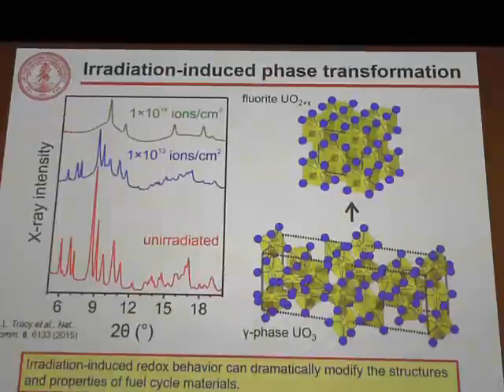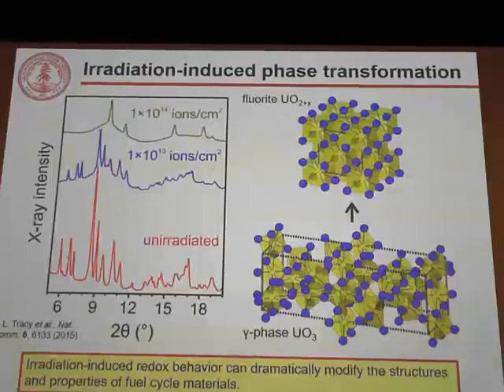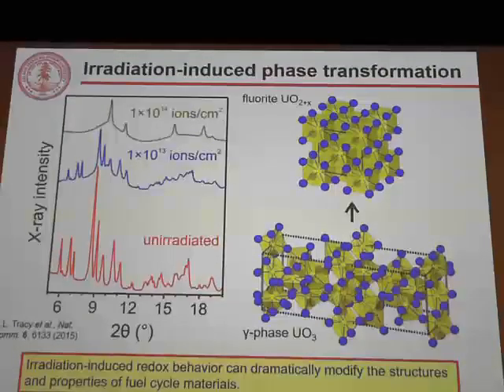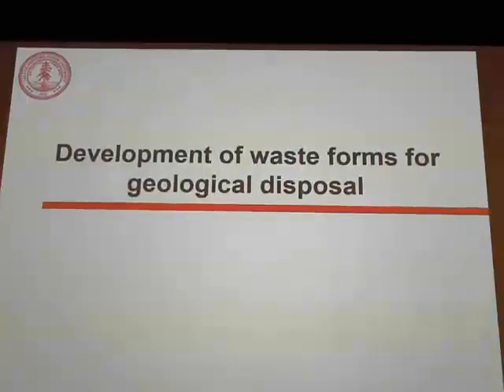We then look at the structure, and as shown in this XRD data, there's a clear transformation from the initial gamma uranium trioxide structure in red to, in green at high ion fluence, a fluorite structure typical of UO2 or UO2+x. So here, this irradiation-induced redox behavior, which I've talked about, dramatically modifies the structure of this material, and we can predict that modification by understanding what happens to the chemistry of a material and how that chemistry is coupled to the structure. This allows us to predict how fuel cycle materials will behave in various extreme environments if we understand the mechanisms of degradation, of transformation.